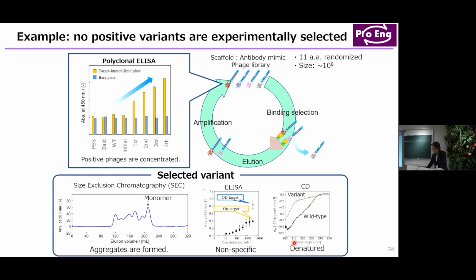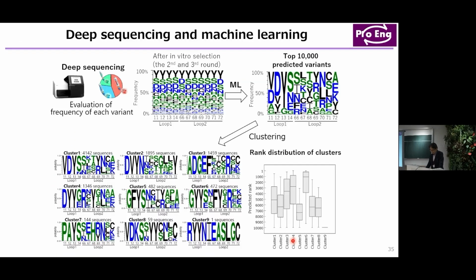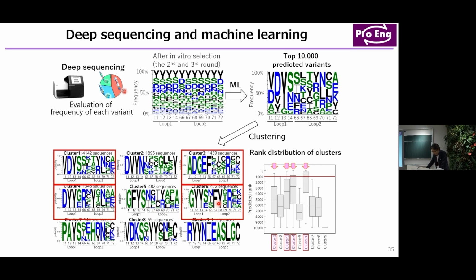By using this data, I tried to find some antibody mimic fragment with affinity for the target. So I also applied these deep sequencing NGS data as training data, and then we selected the top 10,000 variants. After that, we clustered them and separated them into nine groups like that. When we see these four groups, they contain about the top 1,000 variants in this library.